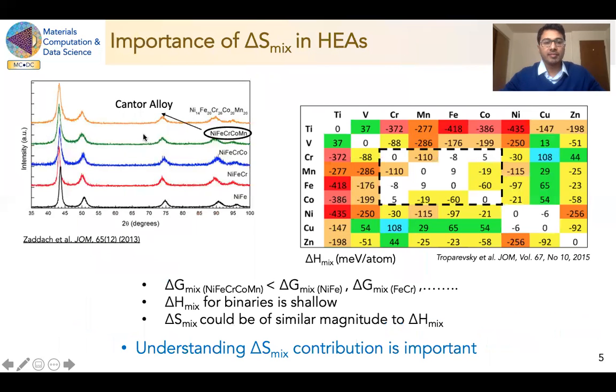In this slide, the left figure shows the XRD pattern of various alloys. Among these alloys, there is the Cantor alloy, which consists of 5 elements. Cantor alloy is one of the important high entropy alloys, and it is a single phase solid solution alloy. Meaning the Gibbs free energy of this Cantor alloy should be smaller than the Gibbs free energy of its constituent binary alloys, as you can see in this expression.